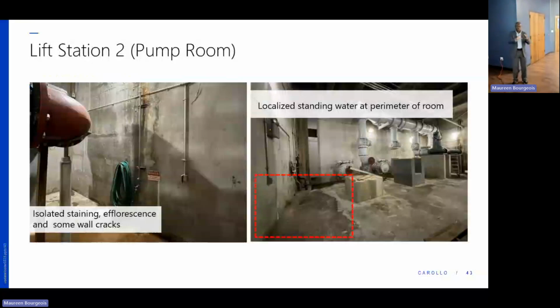Really, when you have a crack, usually in the concrete wall or in a slab, water begins to migrate through it. As the water migrates through the cracks, it's going to react to the chemicals in the concrete mix or in the cement. As the water gets to the surface, it gets evaporated, and then it leaves behind these chemical deposits, whitish in nature. That process, with that deposit being left, is what we call efflorescence. Next slide will show a zoomed in picture of what one of them looked like.